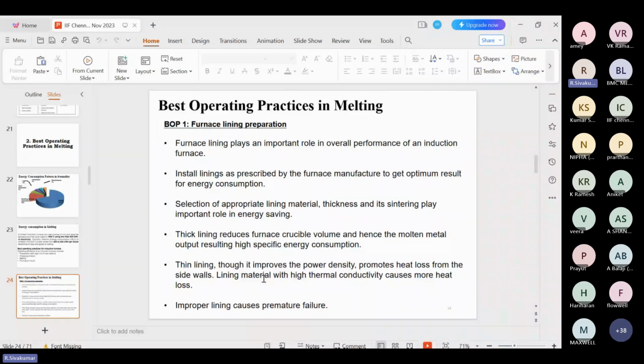Normally, after the lining is completed, in the initial first 50 heats the capacity is 1 ton. The furnace power capacity is 750 kilowatt, so maybe you take one tap every 50 minutes. After the 50th or 51st heat, you face some problems because more slag is accumulating inside and the lining is also slightly affected, so your capacity is reduced. The melt time is also increased. Due to this, the overall energy consumption is also increasing.